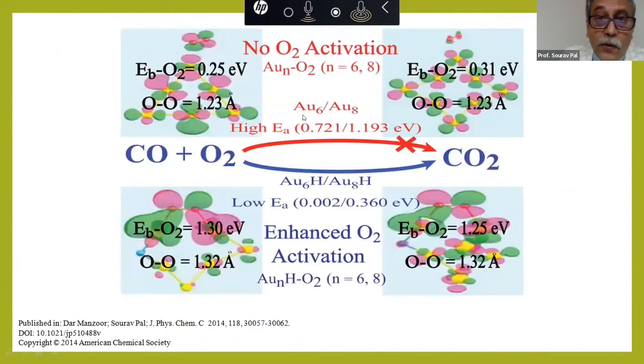Another very interesting work was again a pristine gold cluster, and I told you about this. If you look at the oxygen activation, you can see it's just 1.23 angstrom. The binding energy is just 0.25, 0.31. But as soon as you put hydrogen chemisorption, one can see that the bond is elongated from 1.23 to 1.32, and the binding energy also increases. So that basically activates the oxygen molecule, and eventually that facilitates the CO oxidation reaction.